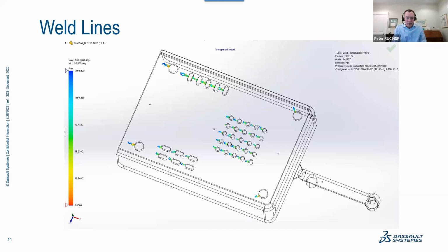So all of these through holes that you see here, we're picking up the weld line prediction on all of them. And some might look at that and say, well, that's a relatively simple and easy thing to do. I would say not so much, because without going into all the detail of predicting weld lines, depending on how you tune your solver, it's very easy to overpredict weld lines or underpredict weld lines. Sometimes it's very difficult to tune your solver to the point where you can just accurately pick up every weld line that's physically occurring, and then also avoiding a lot of noise that might otherwise occur.